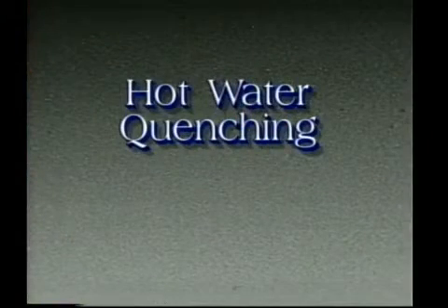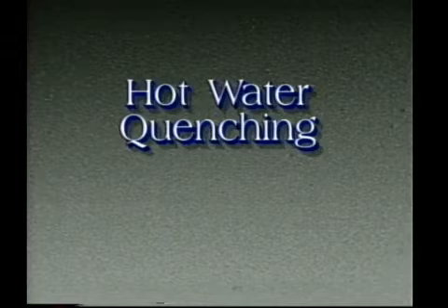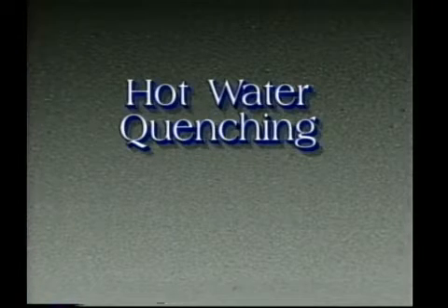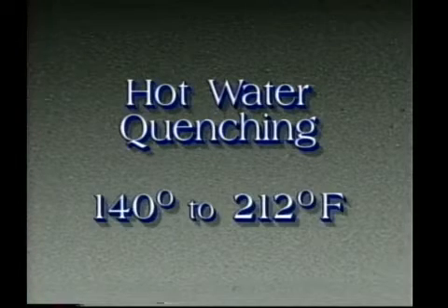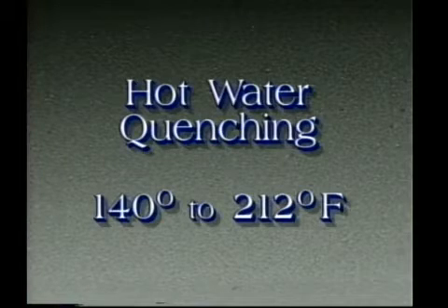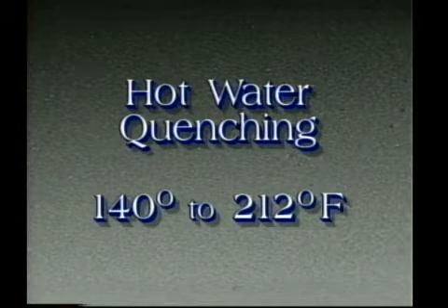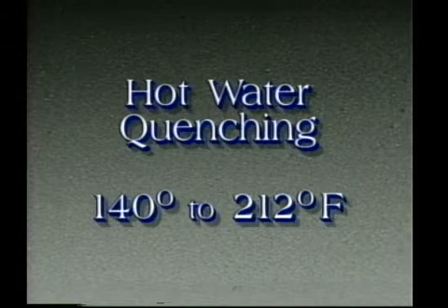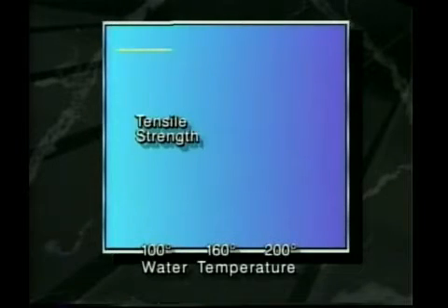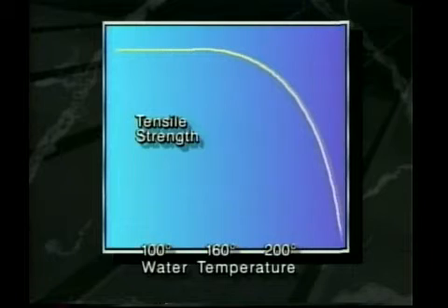In an attempt to achieve, first, maximum distortion control in thin sheet metal parts, and secondly, minimum residual stresses in forgings and castings, hot water quenching is sometimes used with moderate success. Temperatures used are from 140 degrees to boiling. The quenching characteristics of a water quench tank are significantly changed by heating the water. To illustrate this fact, a property loss curve for 7075 alloy is shown here.